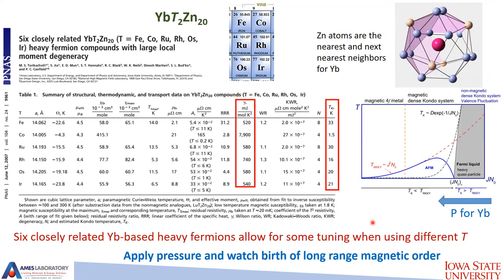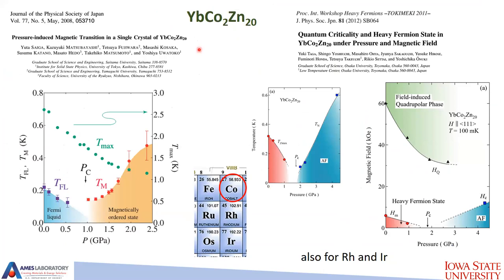At the time of the start of this project, we were thinking, okay, we have Doniach's phase diagram. We're sitting somewhere here in the heavy Fermi liquid. Let's apply pressure, move, and have a magnetic transition, and let's see how it happens. This was done, for example, for Ytterbium Cobalt 2 Zinc 20, where data were consistent with Doniach's phase diagram, although there was an additional field-induced quadrupolar phase, but it's an additional bonus.